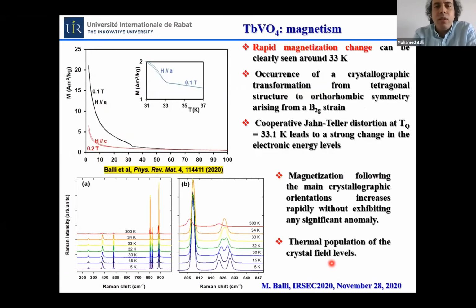Now I will show some results concerning this compound. Here is given the magnetization as a function of temperature for the terbium vanadate compound, reported along both the A-axis and C directions. As can be seen in this figure, the magnetizations involve a giant anisotropy with the magnetization axis along the A direction, and around 33 Kelvin we can observe a fast change in the magnetization. This fast change is due to the lowering of crystallographic symmetry from tetragonal to orthorhombic structure that takes place exactly at 33.1 Kelvin.